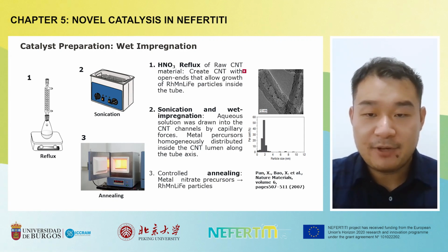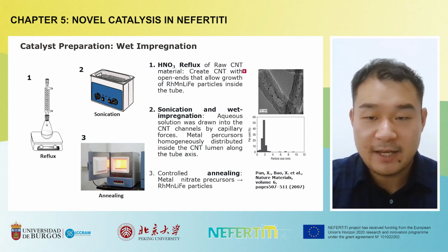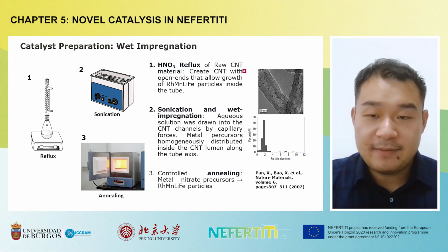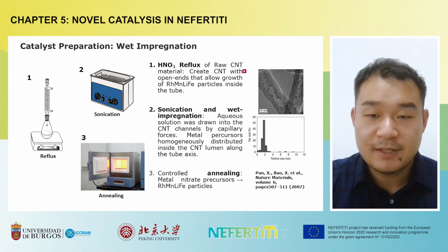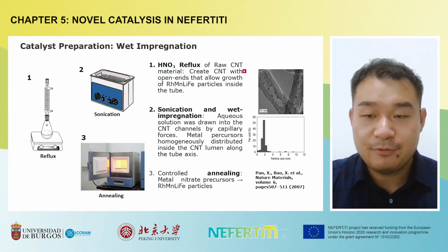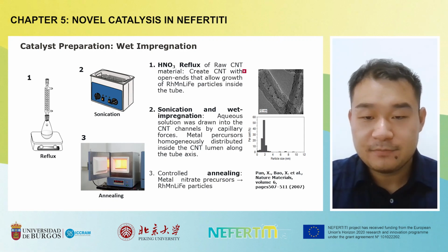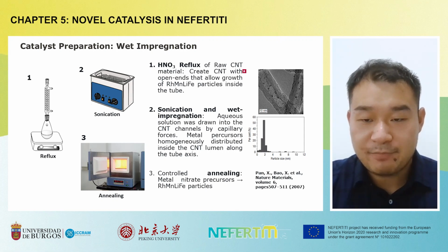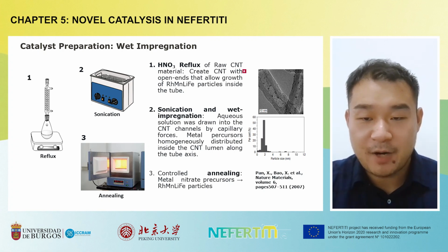We prepare aqueous solutions and draw them into the carbon nanotube channels by capillary force during the sonication so that the metal precursors can homogeneously distribute inside the carbon nanotube lumen along the tube axis. And later we dry the material and anneal the catalyst so that we turn the metal nitrate precursors into promoted rhodium-based particles.